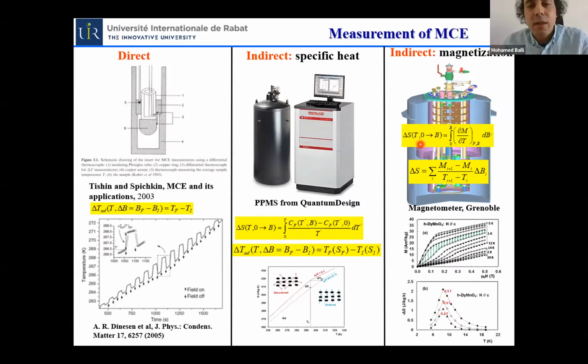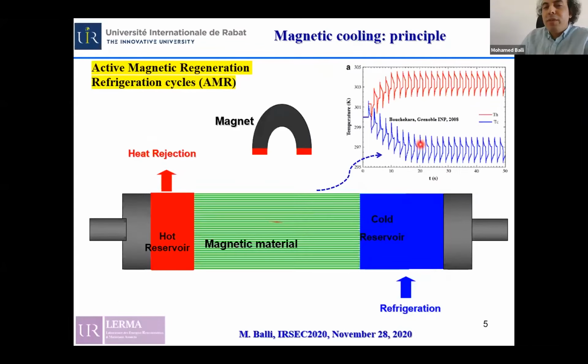There is an interesting point I want to mention, which is that the temperature of magnetocaloric materials makes for a more efficient and serious magnetocaloric device. Fortunately, this magnetocaloric effect in a refrigeration process can be amplified by using specific thermodynamic cycles called AMR cycles, active magnetic refrigeration cycles. In a magnetocaloric device, each AMR cycle breaks up into 4 steps.